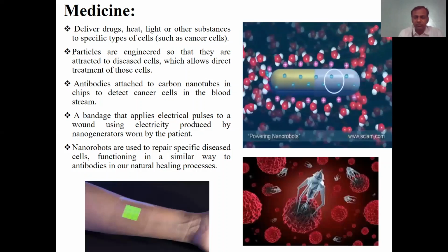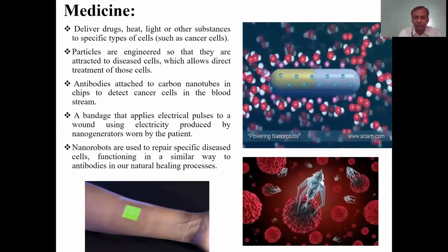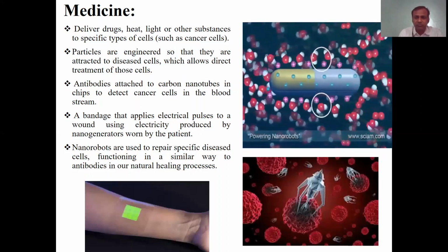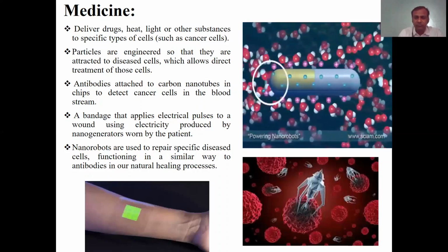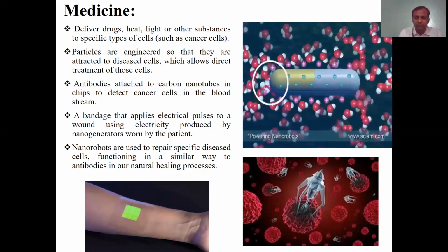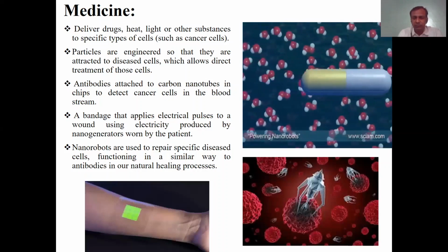The electrons travel through the rod towards the gold end. The protons travel along the surface in the same direction. Because they have a positive charge, they attract water molecules and drag them along for the ride. At the gold end of the journey, the electrons and protons catalyze hydrogen peroxide, breaking the molecule into 2 water molecules. This allows the rod to overcome the viscosity of the fluid and move forward.